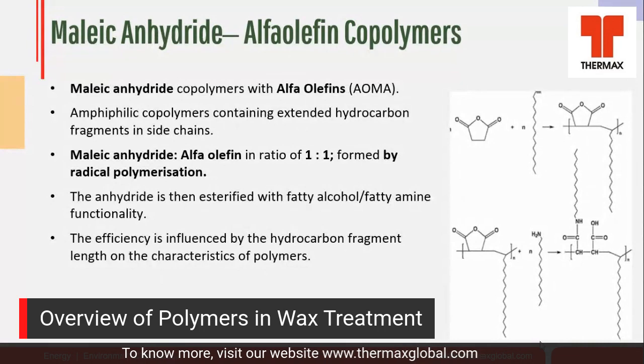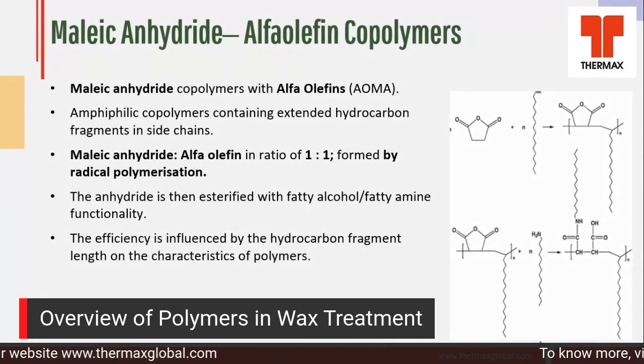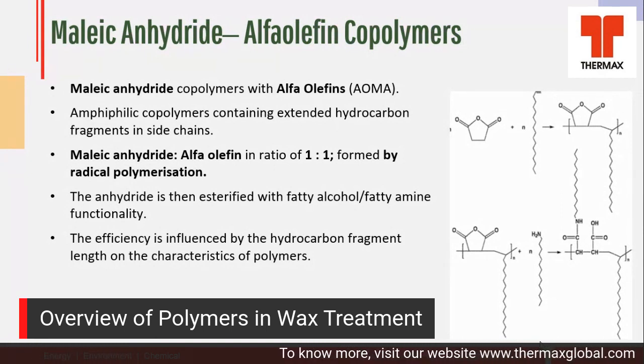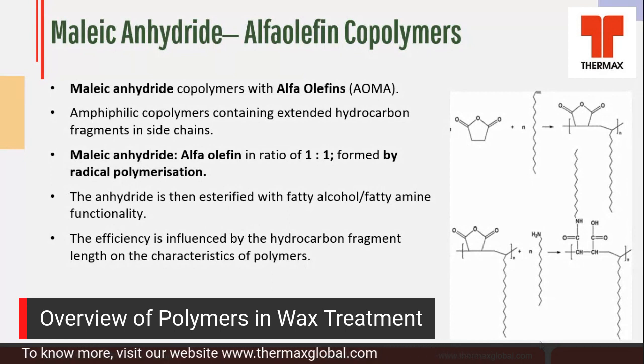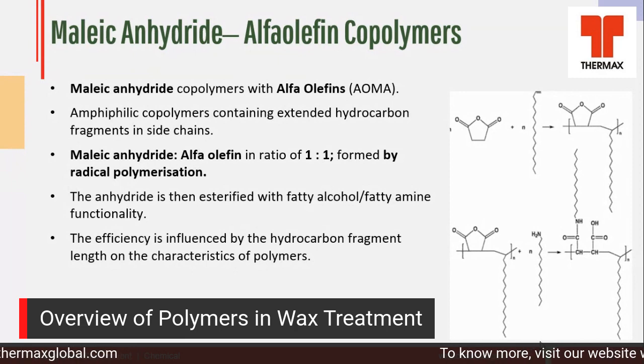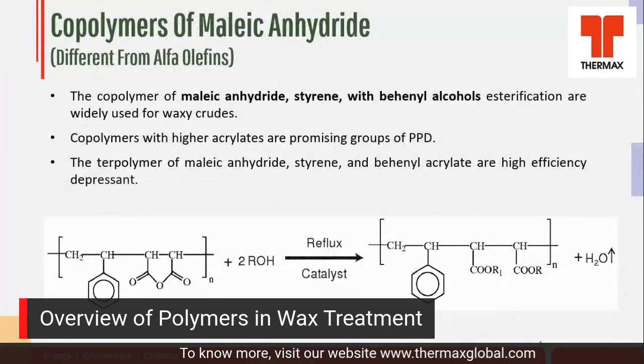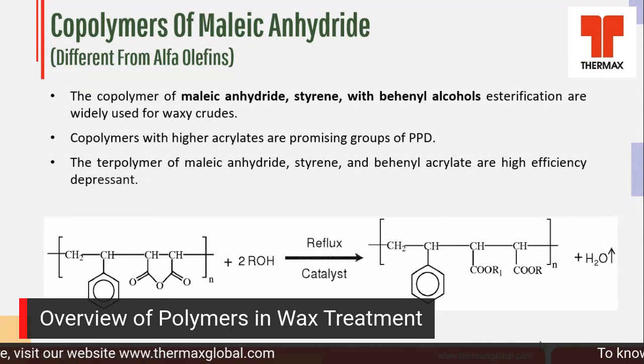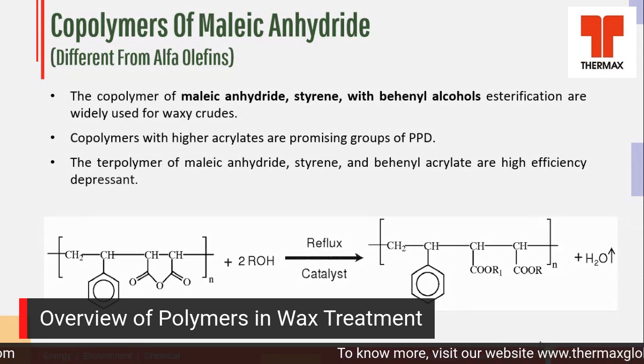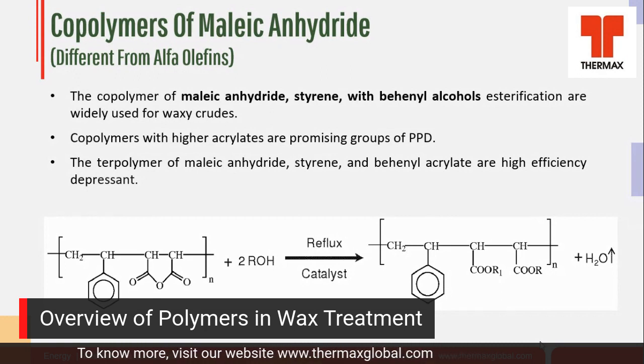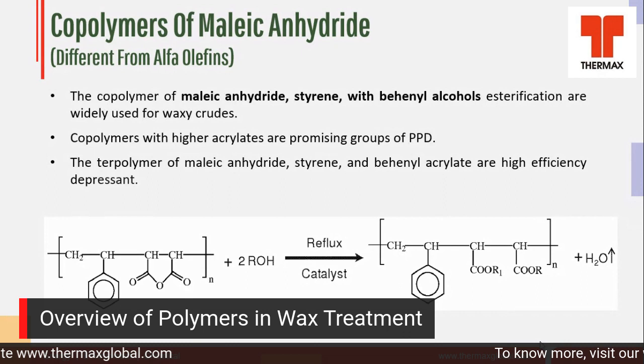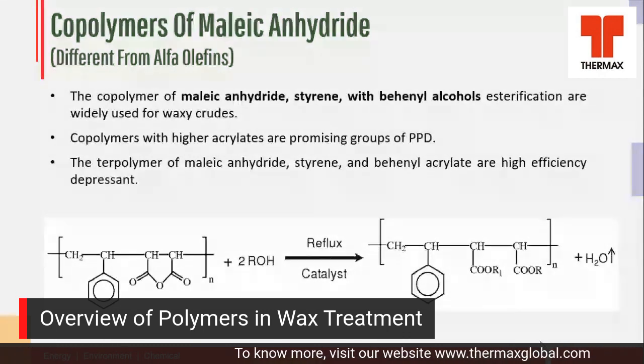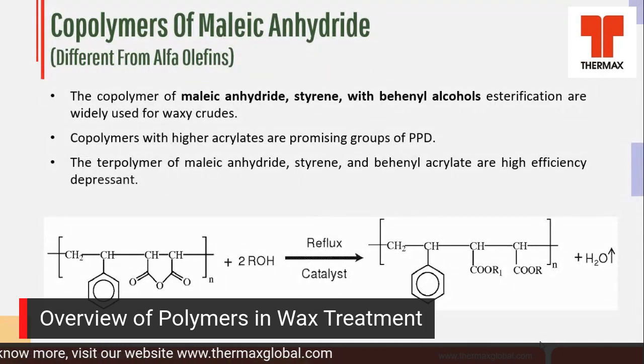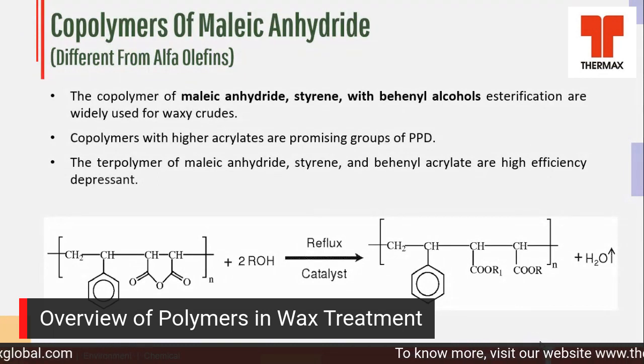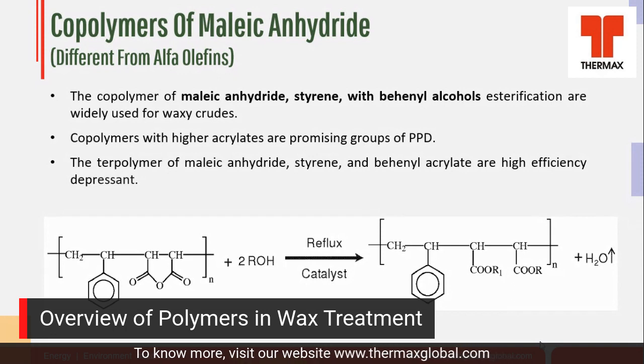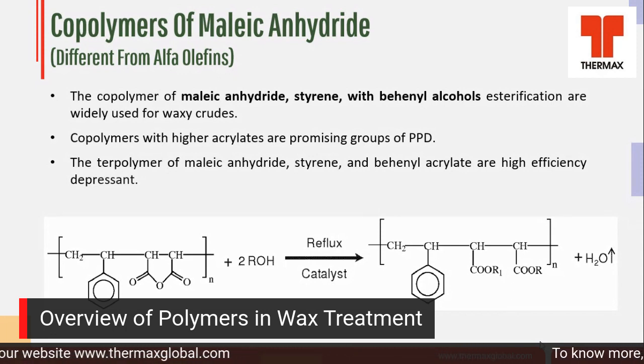Next one is the maleic anhydride alpha olefin polymers. These are used extensively nowadays. One mole of maleic anhydride and one mole of alpha olefin are copolymerized, and then the maleic anhydride is esterified with fatty alcohols or fatty amines. There are also other maleic copolymers, and the most popular is the styrene maleic copolymer. Here also one mole of styrene is reacted with one mole of maleic anhydride to get a copolymer, and again this maleic anhydride is esterified with fatty alcohol. You can see the reaction mechanism below. And this esterification can also be altered, by 1:2 mole or 1:1.5 mole or 1:1 mole, to see the efficacy.